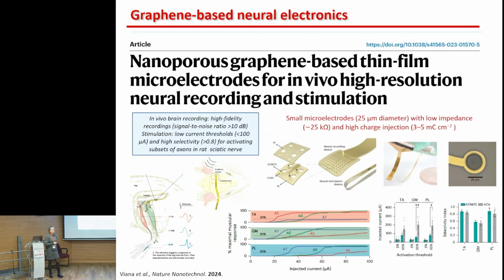There are important contributions on the use of graphene by other mates of ours, in this particular case Jose Garrido from the ICN2. They published this very nice piece of work in 2024 in which they used graphene for the development of microelectrodes, for in vivo high resolution neural recording and stimulation. As you can see here, they get very high fidelity recordings, and they are able to stimulate at low current thresholds and with high selectivity, achieving this in a very small microelectrode size, as you can see here, 25 microns, and low impedance.